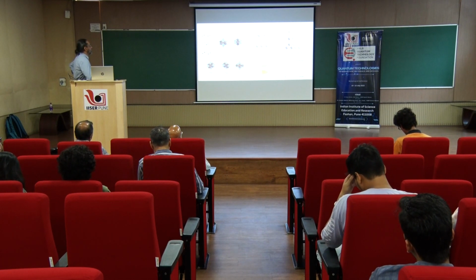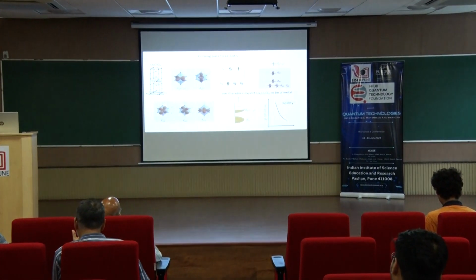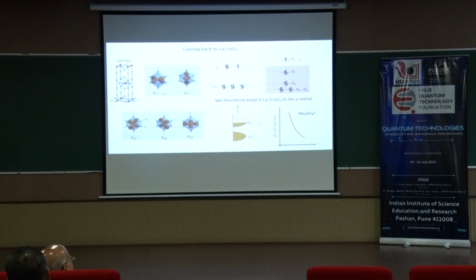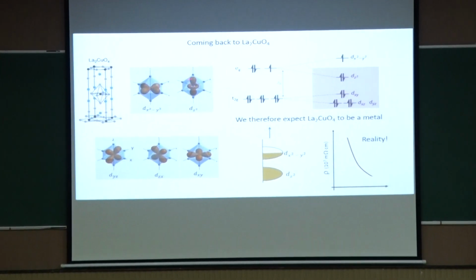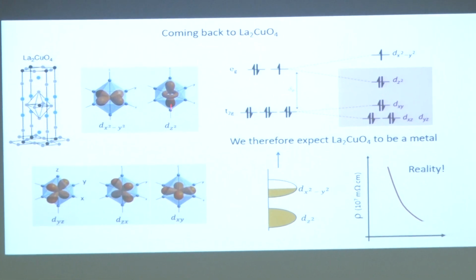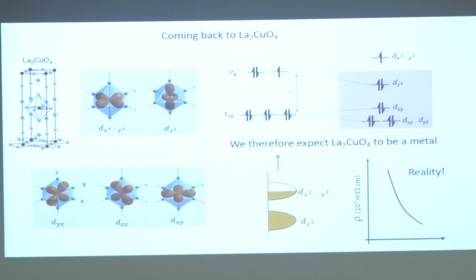these 5 d orbitals. So, z square and x square minus y square orbitals, they are directly seeing the oxygen ions. So, in this case, for instance, the x square minus y square lies in the xy plane, and for the z square case along the z axis, and because of that, if the electron has to reside on the z square orbital, it has to face more repulsion from the oxygen sitting here compared to the situations depicted over here, because in this case the lobes of the d orbitals are pointing in between the oxygen ions. So, therefore, the repulsion is less compared to the repulsion in these cases.